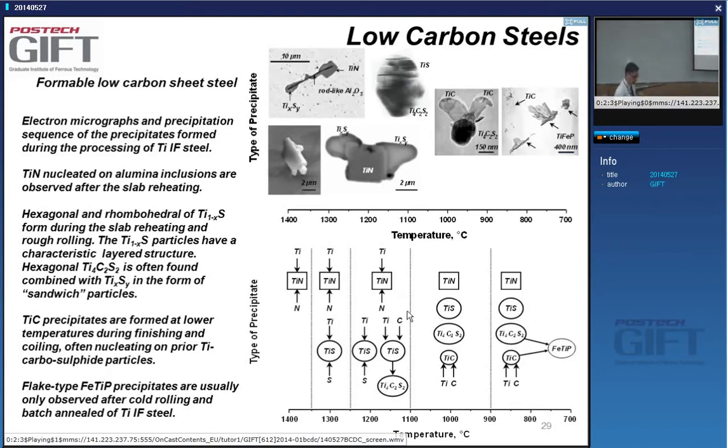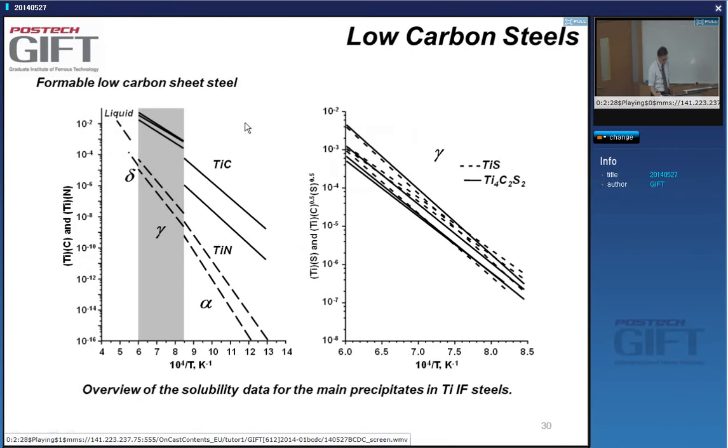The steel industries then developed what are called the titanium niobium IF steels, where the nitrogen is stabilized by the titanium and the carbon is stabilized by the niobium. And there is no need for these large excess titanium values. So important here, I want to stress this,